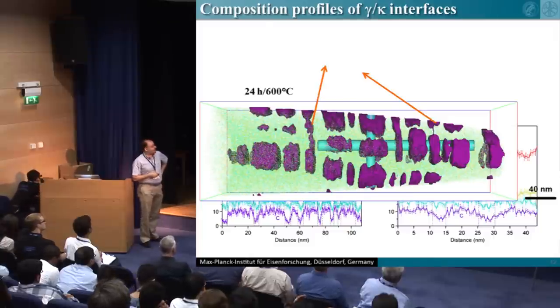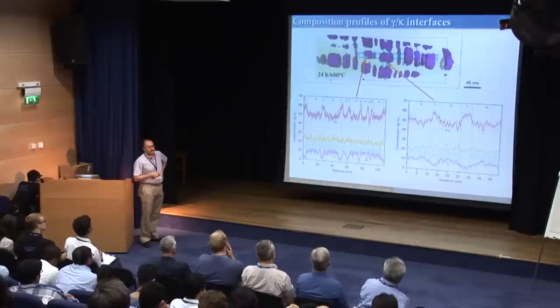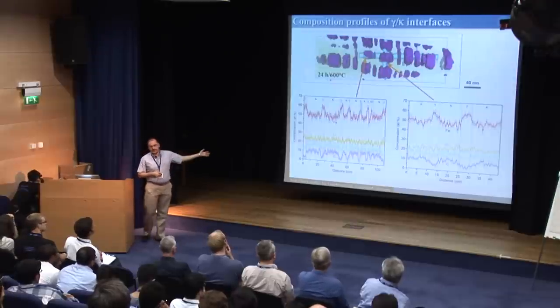One can immediately see something pretty interesting: the ratio between iron and manganese is 2:1. That means that we don't have a stoichiometric phase. We are off the proposed stoichiometric phase. But on the other side, we have extremely coherent interfaces. So for this system, it's the right system to go.